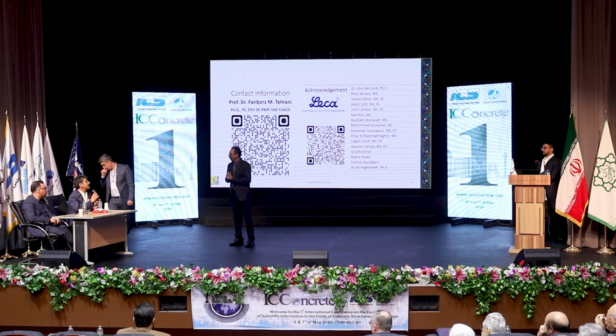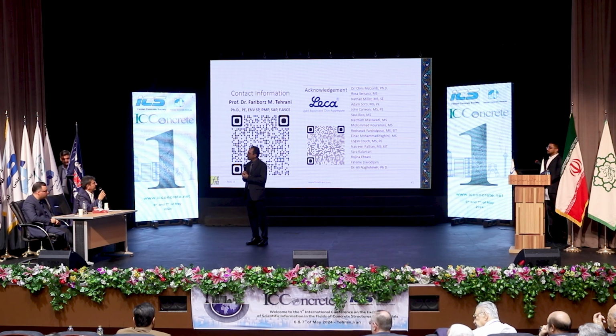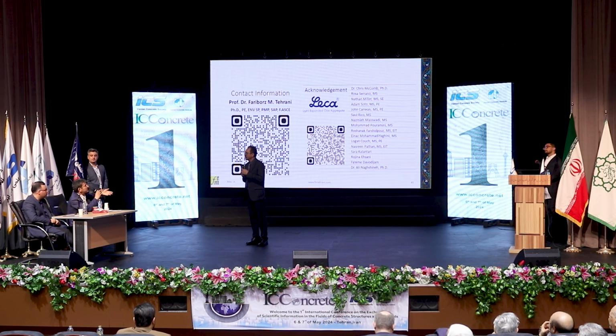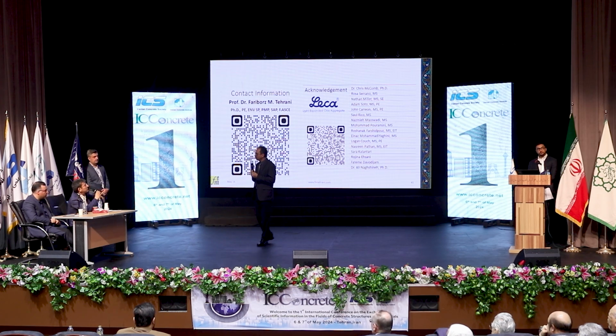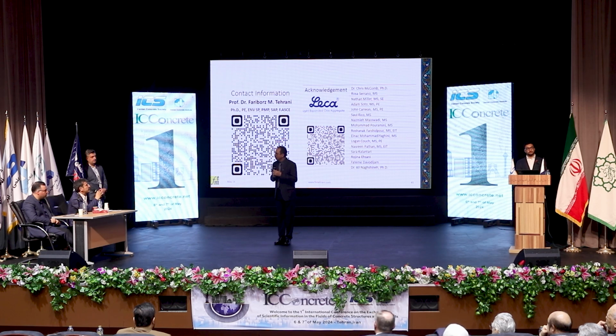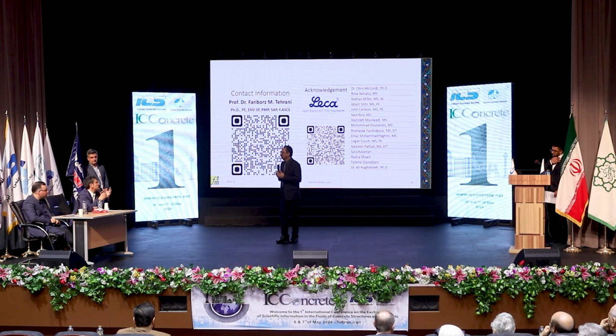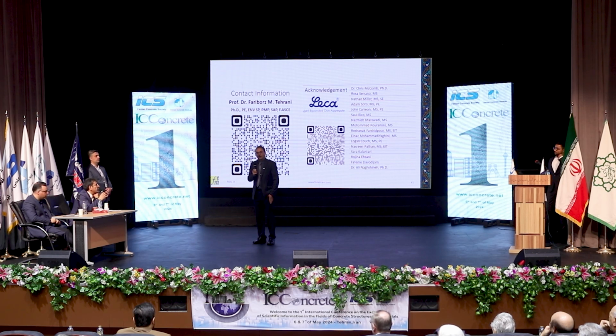I think it's true just for low water cement ratio, in fact. I mean, autogenous shrinkage or internal curing is necessary just for low water cement ratio, less than 0.5, 0.4, something like this. Normally, in our concrete, the water cement ratio is higher. Normally we don't need internal curing for the most used concrete, for example, for pavement.